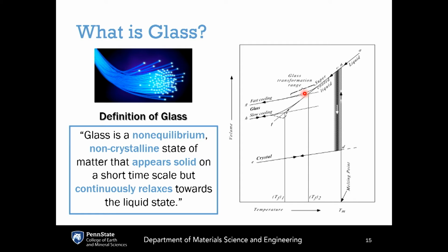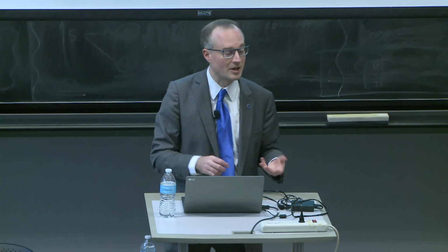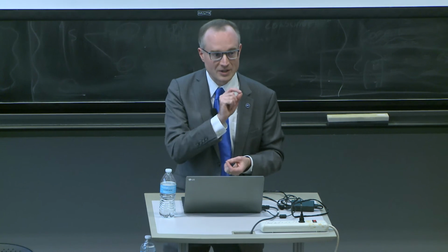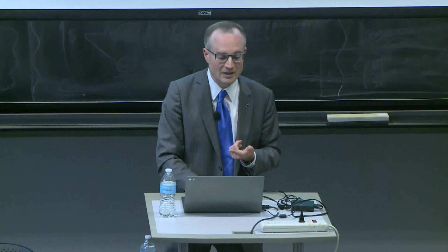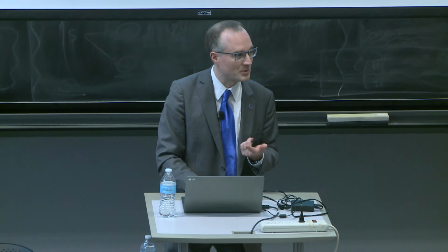So the glass transition, this transition between the liquid and the glassy state, is key to understanding what glass is. It comes from the liquid. It will return to the liquid if you heat it back up. The structure of a glass is very similar to the structure of the liquid. They're continuously connected together. This is what distinguishes glass from amorphous solids. Amorphous solids do not have a structure similar to the liquid, and if you heat them up, they do not undergo this continuous transformation to a liquid.